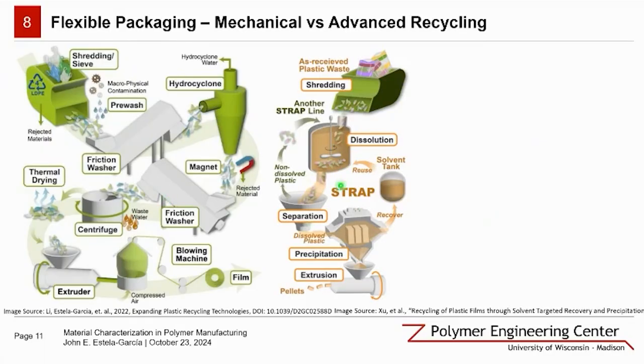Now we can look at an advanced recycling method. This method is called solvent-targeted recovery and precipitation, STRAP. So this process focuses on using specific solvents to target polymers in mixed plastic waste. So we have here as-received plastic waste that is being fed into a dissolution tank with a specific solvent that is targeting one plastic in that material. So the plastic that is being targeted dissolves inside of the solvent, which can then be precipitated outside. So the non-dissolved pieces can then be fed into another dissolution chamber to recover another specific plastic. This allows us to achieve higher purity in recovered polymers, but it does involve dissolution, precipitation, and solvent recovery steps.